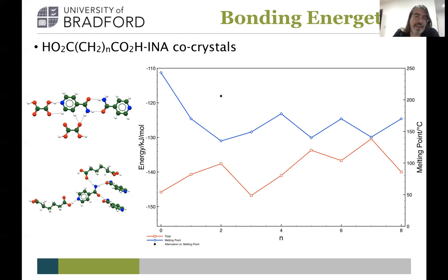But again, it's the same hydrogen bonds as that, so it sums up to something of a similar number. It is slightly less than the dimer would be. And so if we plot that against the melting point, we see an almost perfect mirror-plane kind of match. So we'd expect the ones with the strongest interactions to have the higher melting points and so on. So we get a general trend that as we increase the length of the chain, we reduce the strength of these interactions, and so we get a lowering of the melting point. We also see the oscillation between odd and even that we see in a lot of melting point data. We see that towards the end here, at least, in terms of the strength of the energy.